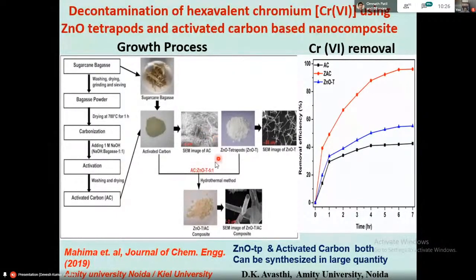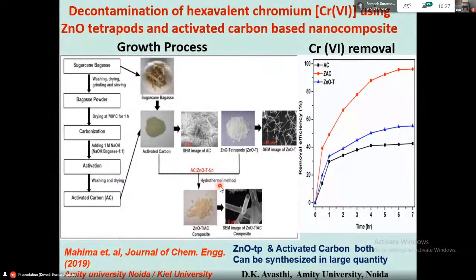The other thing is that we have zinc oxide tetrapods, which are produced by a flame transport process. But these two things are mixed, and I'm not going into detail how this is made, because this is well established and is a patent, and we have a collaborator, Dr. Mishra, now in Denmark, who gives this material for a collaboration, and this work is also in collaboration under that. So this zinc oxide tetrapod, which is shown here, this is an SEM image of that. These two things are mixed together and put in a furnace by hydrothermal method.